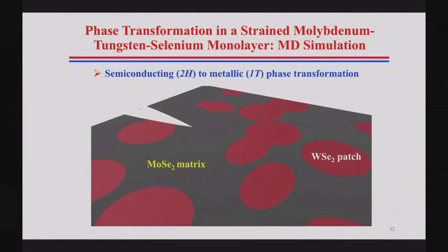The practical implication would be a damaged substrate would destroy, I don't know, a transistor or something? Right. But the nice part is, instead of destroying, supposing you want to switch between semiconducting and metallic, strain the system. It's not necessarily just a crack, just strain would do it. So with strain, you can really change the electrical properties of the system. Right, which also means you can measure very fine forces this way, right?